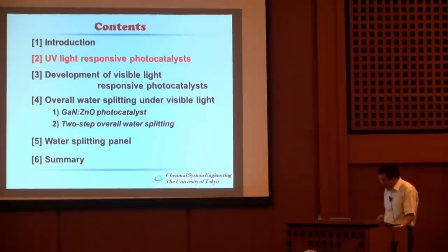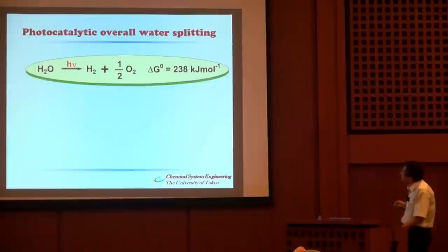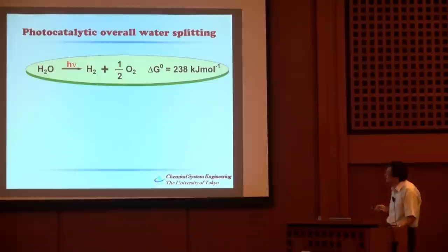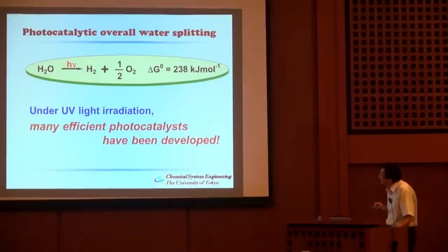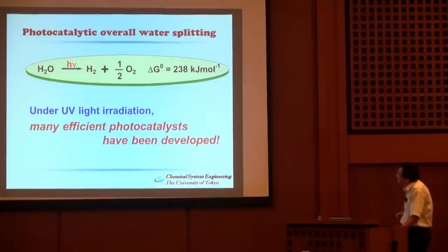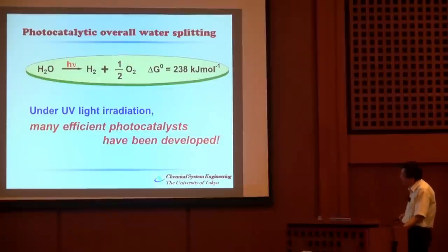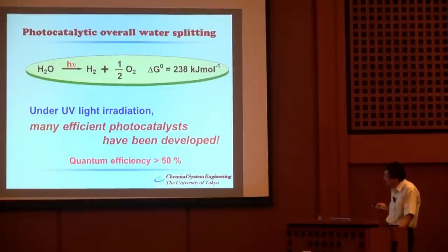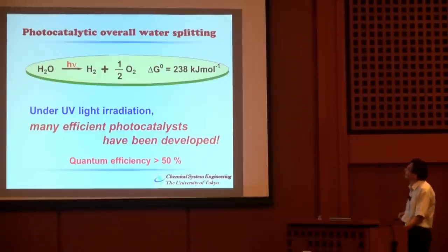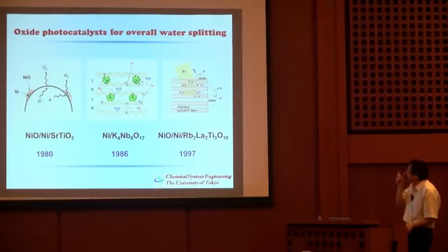Now, UV light-responsive photocatalysts. We have been working on this type for more than 30 years, and at present, including many other groups worldwide, it is possible to say that under UV light irradiation many efficient photocatalysts have already been established. In some cases the quantum efficiency — not the solar energy conversion efficiency, but the quantum efficiency — can exceed 50 percent.